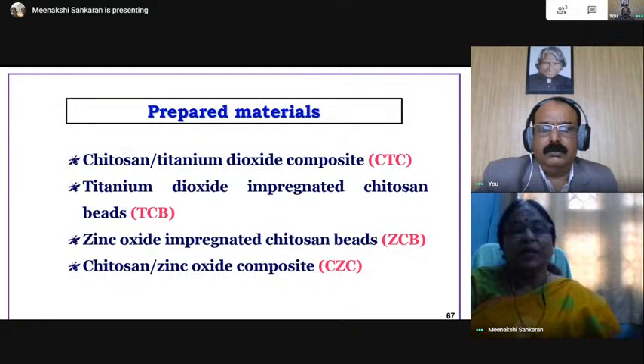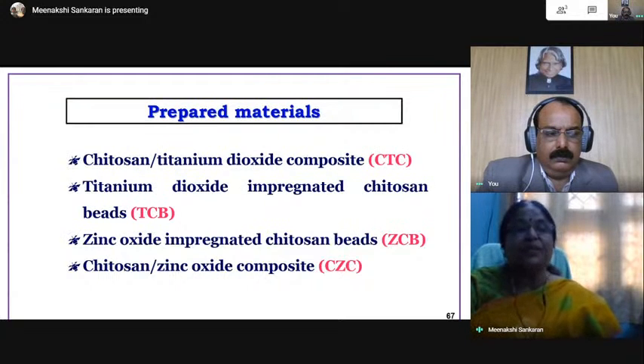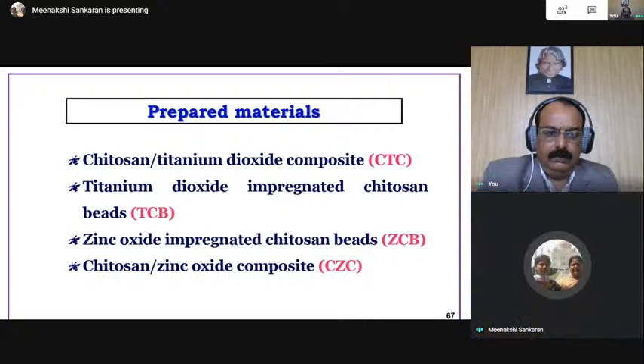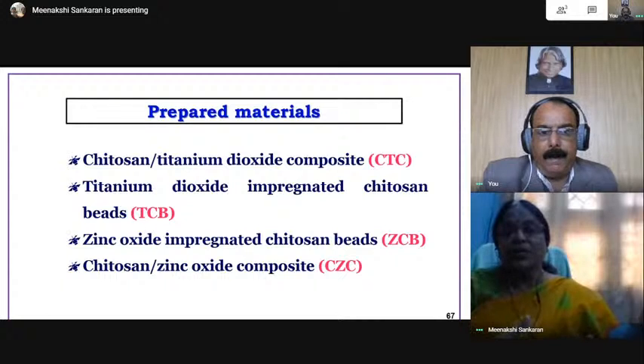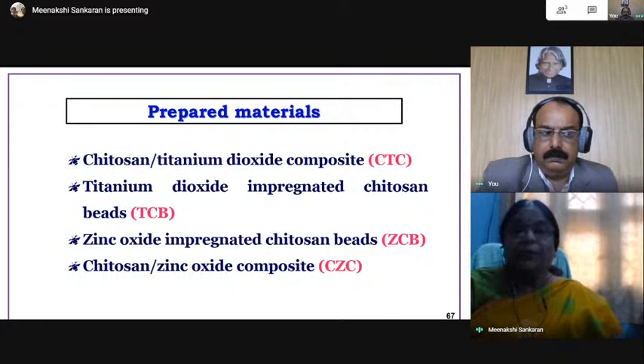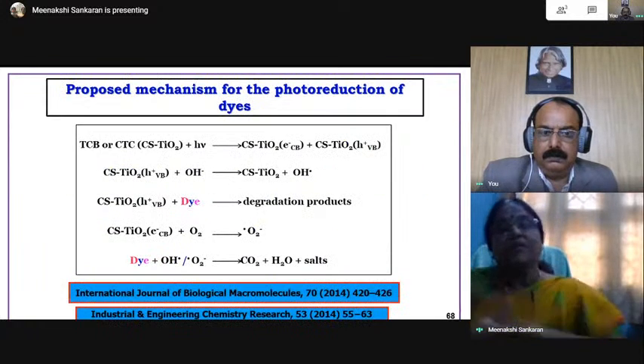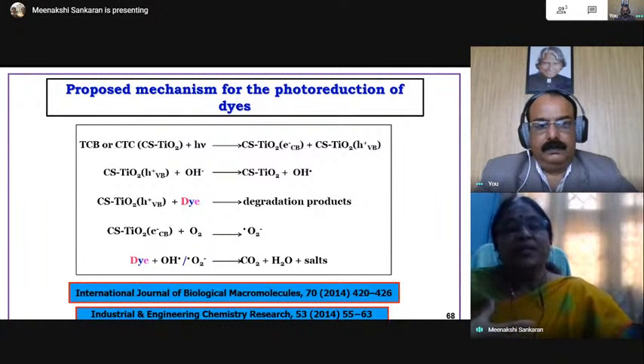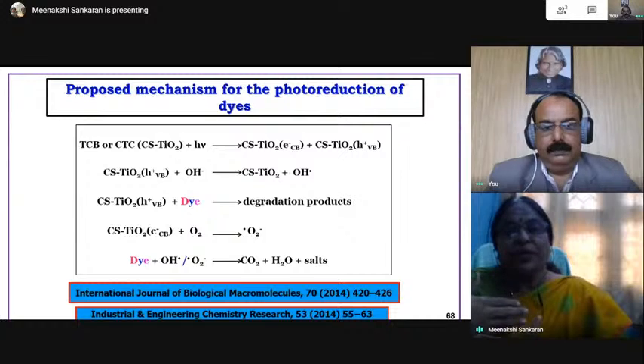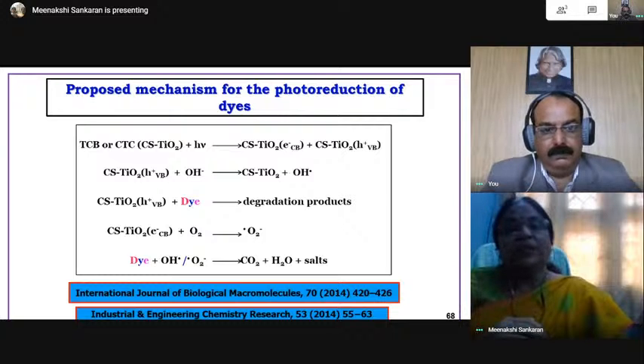So we have prepared chitosan titanium dioxide composite, titanium dioxide impregnated chitosan composite beads, and zinc oxide impregnated chitosan beads. We have mixed photocatalyst and chitosan, and those materials have been used for degradation of dyes as well as chromium removal. The same mechanism applies: when energy is given, there is formation of a hole and electron pair. They should not combine again, because if they combine, there will not be any photocatalytic reaction. So they will remain as such.